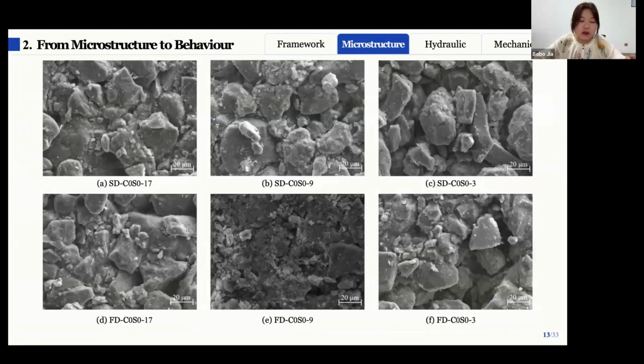And there are corresponding SEM images of the C0 S0 samples under slow and fast drying at representative water contents. The first and the third columns correspond to the initial and final states, while the middle column, at 9%, represents the stage at which the third peak in the micropore range first appears.